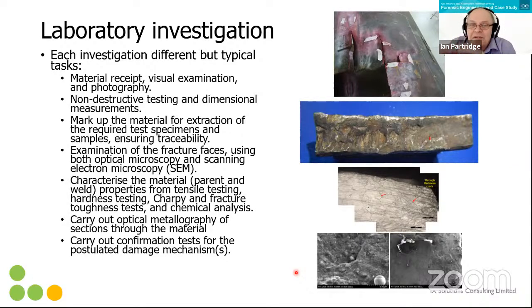Then you would characterize the material property. So one of the big questions is, was the material correct in the first place? Was it fabricated correctly? You want to remove that from the analysis early. If it was created correctly, you want that out of the way. But you want to know what the material properties are, what the load limit requirements are. Then you would carry out metallography. So what you're seeing here, we're getting smaller and smaller. Here you're looking at a crack front at a reasonable macro size. Here you're at an SEM, so you're down at nano levels. That's the fracture face. And so you're coming down in detail, zooming in more and more.